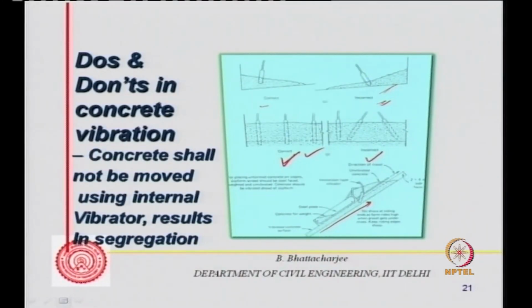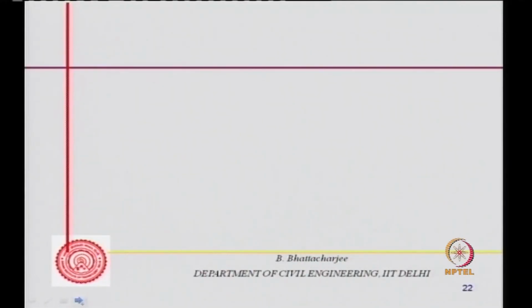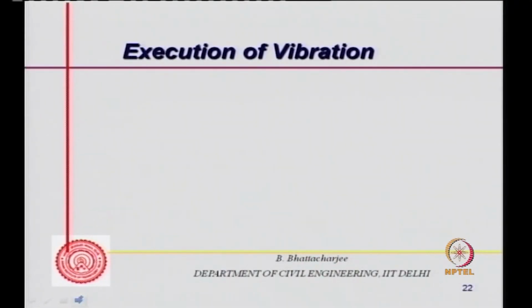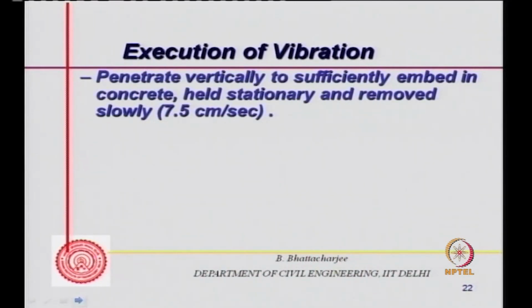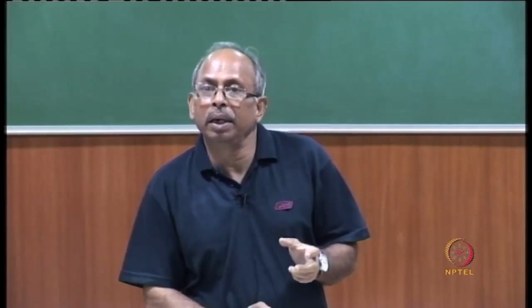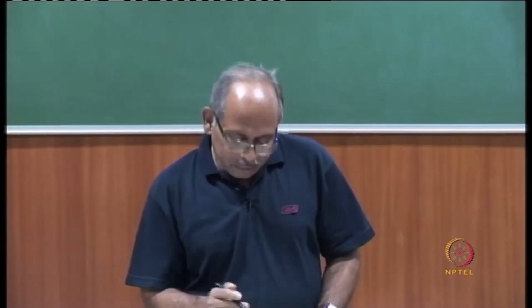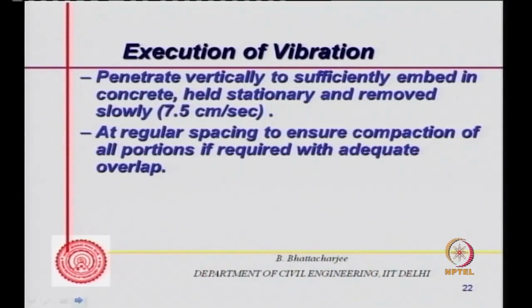The concrete should not be moved using an internal vibrator, which can result in segregation. That means penetrate vertically to sufficiently embed in concrete, hold stationary, and remove slowly, say 7.5 centimeter per second is a good, slow velocity, but one may not be measuring them. But the idea is that when you are taking out the vibrator, it should be taken out slowly.